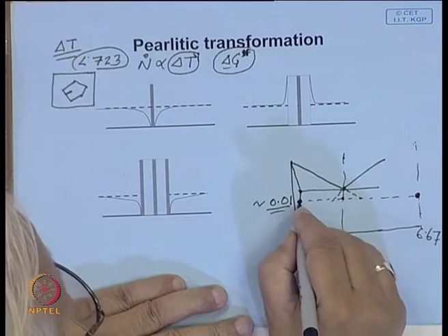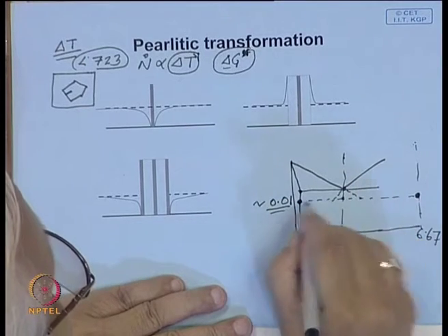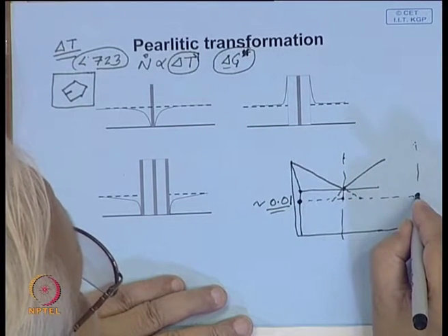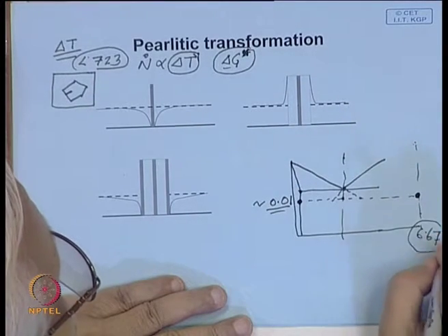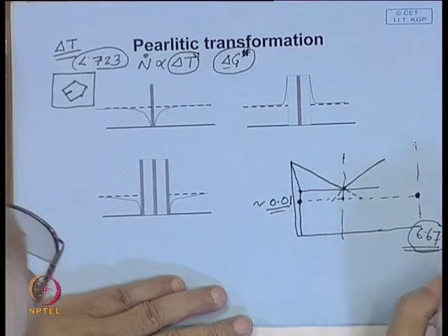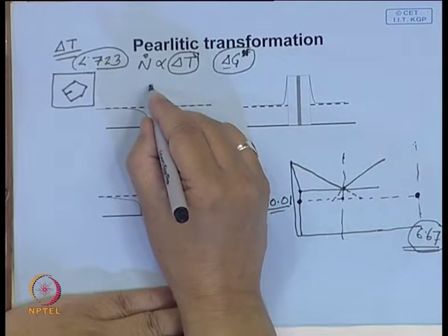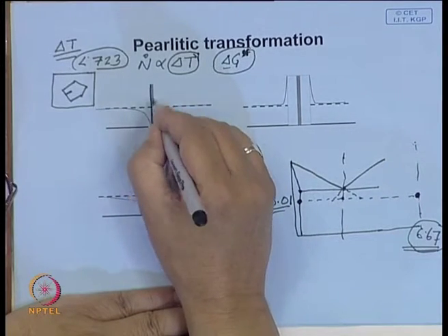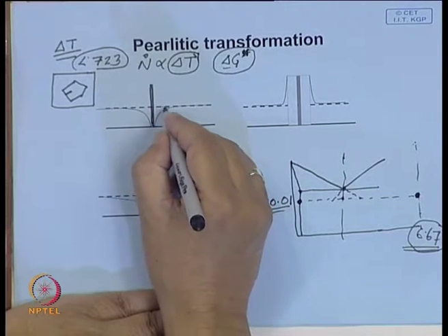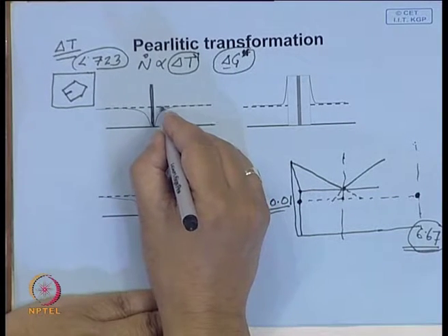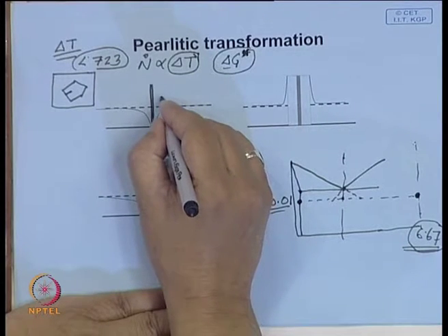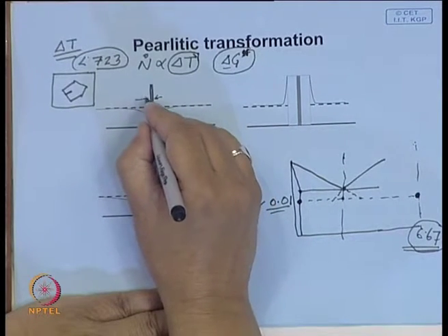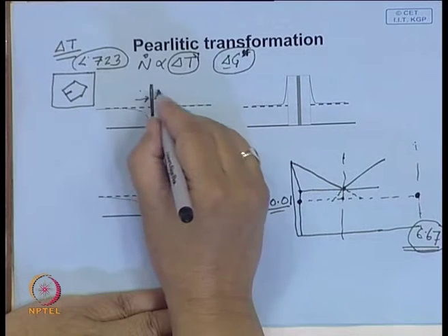So, what happens when cementite nucleates, it will withdraw carbon from around it; for cementite to form you need so much carbon content. So, if a cementite plate forms, imagine it will capture all the carbon atoms from the neighboring region, all carbon atoms from the neighboring region go here to form this cementite.